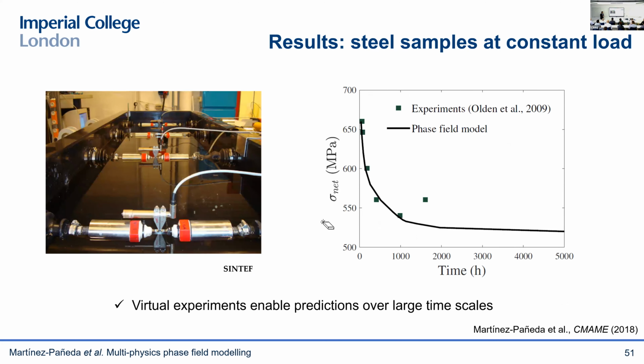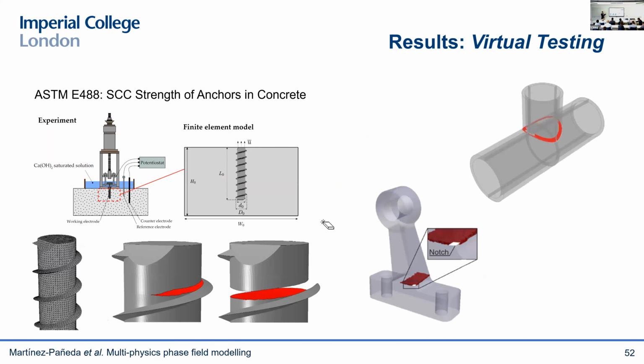And we can do more interesting experiments. So these are experiments done in Norway where they subjected multiple duplex stainless steel samples that contain a notch. They were immersed in a seawater bath to introduce the hydrogen. They subjected all of them to a constant load, each of them to a different load, and they measured the time to failure. And they were hoping that one of them was subjected to a sufficiently low stress that they would not see failure over relevant time scales. But as you can see here, all the samples fail relatively early, but we could take our phase-field model and not only reproduce their experiments, gaining confidence in our predictions, but also run virtual experiments with very large timescales. So we can determine what is this critical stress below which you can load your structures. And we can do anything, that's the beauty of it.